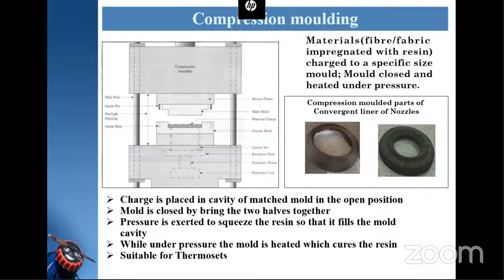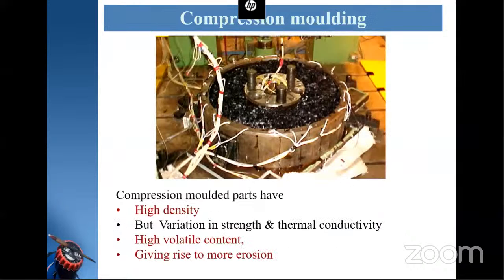Here the charge is placed in the cavity of a matched die mold in an open position. The mold is closed by bringing the two halves together by using a hydraulic arrangement. Pressure is exerted to squeeze the resin so that it fills the mold cavity. While under pressure, the mold is heated and the polymer is polymerized to get nice composite components suitable for highly thick components. So here you can see this is one of the products which we have made.